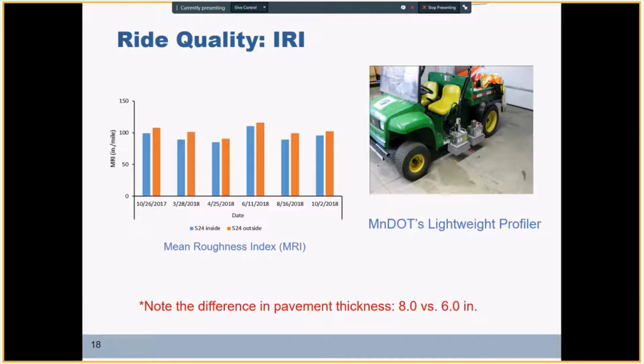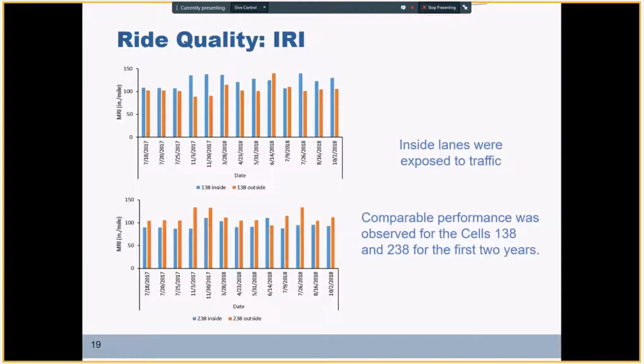Here I have the data for the reference cell with MRI values, mean roughness index values, which is the average of the left and right tire tracks. The numbers are ranging around 100 plus or minus about 10 inch per mile over time, not a considerable variation for the reference cell. And almost the same trend for the experimental sections.